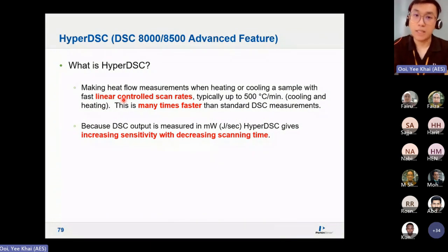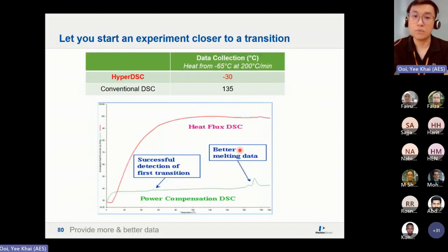So this is hyper DSC, only for DSC 8000, 8500, the power compensation. We can now do linear controlled scan rates many, many times faster. You can go up to 500 degrees C per minute, and still be within control compared to the conventional DSC. What we measure is, of course, milliwatts. Watt equals joule per second. So the faster you heat it up, the time drops, so W increases, because W equals joule per second. So you can use this to increase the sensitivity of the signals. Let me show you the examples later.